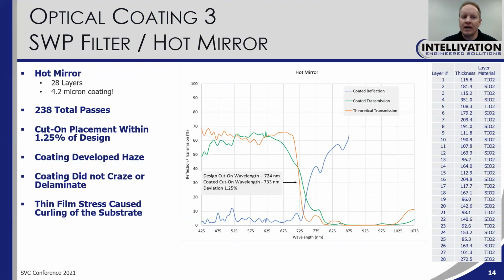The next coating we looked at was a shortwave pass filter or a hot mirror. This was a doozy of a coating. It's 28 layers and 4.2 microns thick. So you can see the full recipe over there on the right. This coating did have some pretty thick layers in it. And so we used many passes just to keep the heat load low on the substrate. It was 238 passes altogether. And the cut-on placement was within 1.25% of the design.